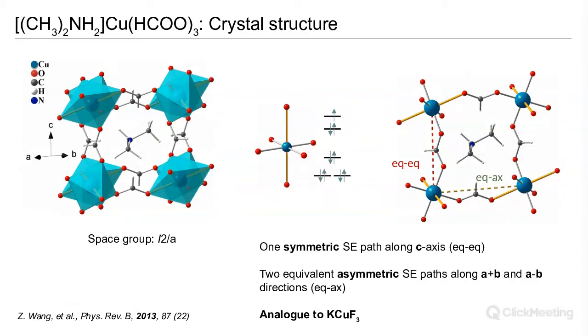Okay, the copper is Jahn-Teller active. The octahedra wants to extend. It does so. This is seen in conventional diffraction, and this then actually creates an orbital structure that is a very good analog to the potassium copper fluoride case. That's what we would predict based upon bond lengths alone. It gives rise to two different exchange pathways. Along the c-axis, we have these, what we label here, equatorial bonds. So these are, if you like, the direction in which we anticipate the magnetic orbitals to lie, creating strong magnetic exchange pathways along c. And then in the ab plane, we have these so-called equatorial-axial bonds, which are these asymmetric bonds between the Jahn-Teller axis and non-Jahn-Teller axis.